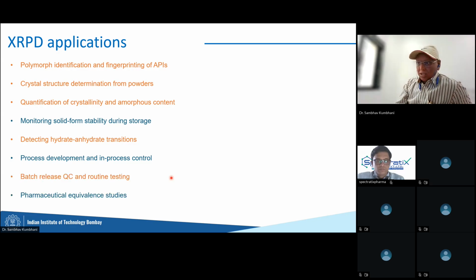Batch release, yes, it is very critical. You do not release a formulation batch without confirming with XRD, for sure. And of course, you want to confirm the equivalence, that this is the same pharma drug from one company to the other. Aspirin from Cipla, aspirin from GVK, should be aspirin. That can be confirmed using XRD.